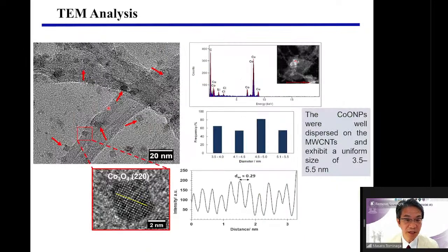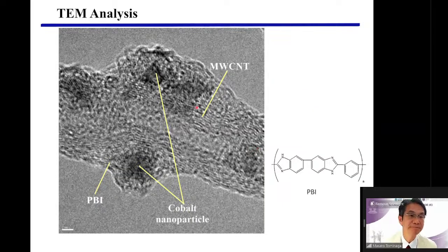Okay, this is a TEM analysis. You can see multi-wall carbon nanotube here, and at the surface, you can see cobalt nanoparticles here and here. These nanoparticles are very uniform, and the size is controlled from 4 to 5 nanometers. And also the surface crystal is usually 2 2 0 of Co3O4. Again, this is a TEM image. You can see a multi-wall carbon nanotube here, and these are the cobalt oxide nanoparticles. And this one is PBI, this polymer.